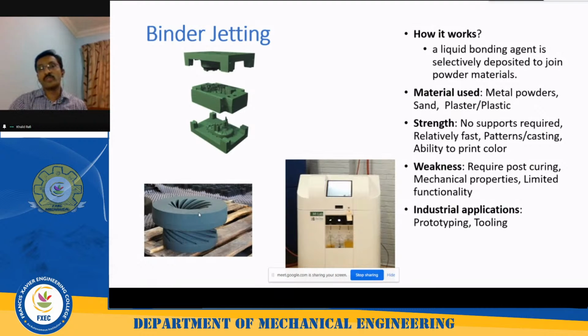But the weakness of this process is that it is a multi-stage process, which means once you finished creating this product, it's only glued with the binders. It's called a green product, and it is very fragile. So what we have to do is, after this, we have to take it to a chamber where you unbind the glue first. That's one stage. And there's a second stage where you have to sinter this part so that you will get the right strength for the application purpose. So it's more like a 3-stage process, but it's more useful when we go for creating sand molds with complicated structures.